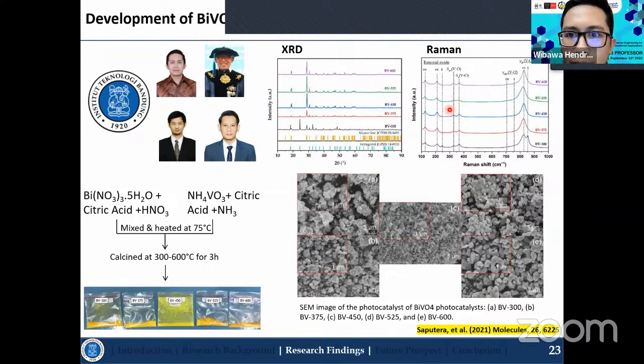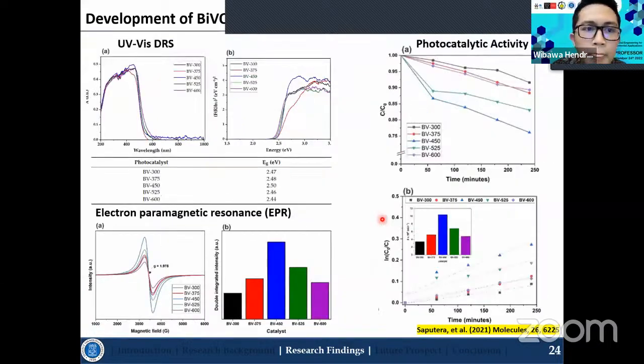And it is also confirmed by using Raman spectroscopy, where at 375 degrees C there is no tetragonal phase, and it is totally transformed into the monoclinic phase. And this is the same images for the photocatalyst of the bismuth vanadate at different temperatures, 300 until 600 degrees C. And we did also different characterizations.